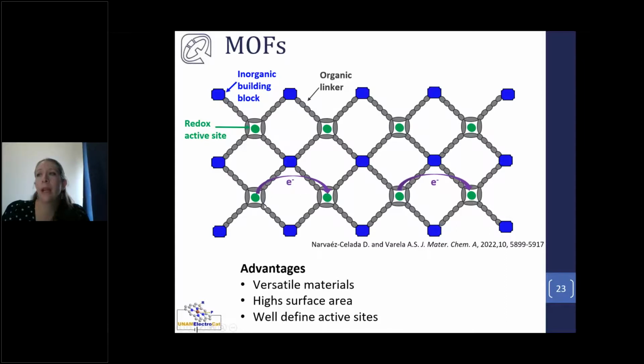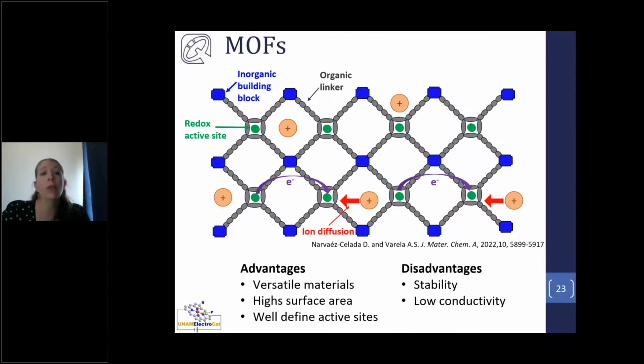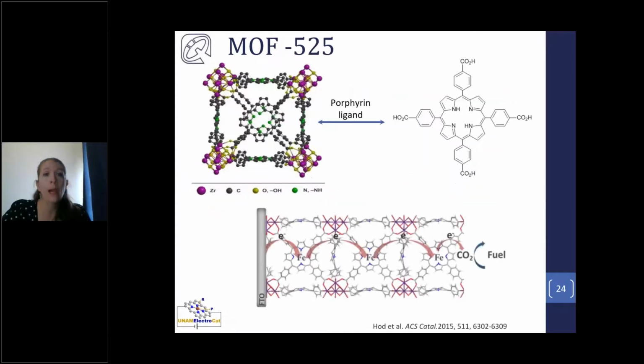So what we will have is that the electrons are going from redox site to redox site, while we will have counter-ion diffusion also occurring. So this is not the most optimal mechanism for conductivity. So we will have a challenge with the low conductivity of MOFs. And then, we have also seen some issues with the long-term stability of MOFs under electrochemical environments. Nevertheless, there have been some successful examples of MOFs used as CO2 electroreduction catalysts.